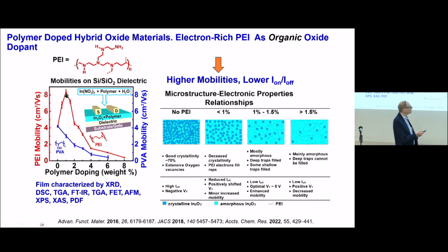You can see that actually the mobility of the indium oxide, when we dope it with a little bit of PEI, really goes way up, and then it levels off and goes down. And you can basically model it. You sort of say, if I have indium oxide, this is its intrinsic properties. But as I begin to dope it now, it turns out that indium oxide has oxygen vacancies. If we fill those with this polymer, and we've done XPS, XRF, X-ray diffraction, everything you can imagine, you reach a point where we filled all the traps. This should be traps and not wraps. And it maximizes. And then as you add more and more polymer, ultimately it's filled the traps, but you begin to lose mobility because there's less and less indium oxide.